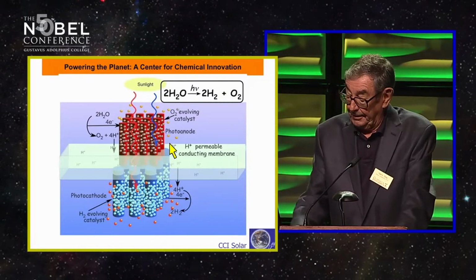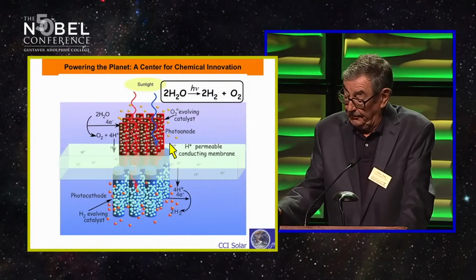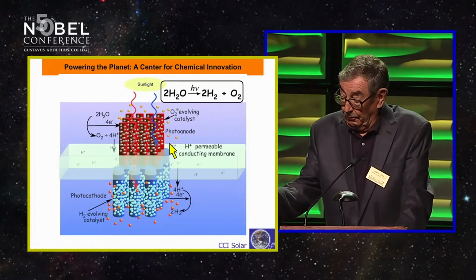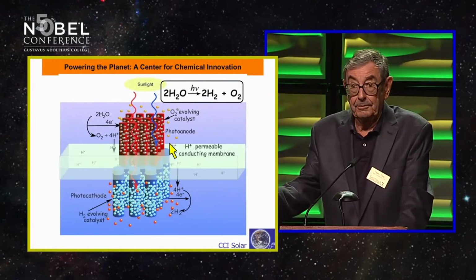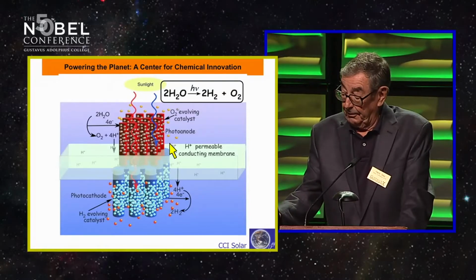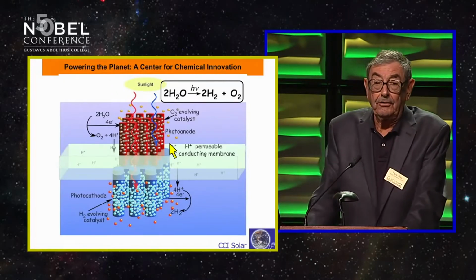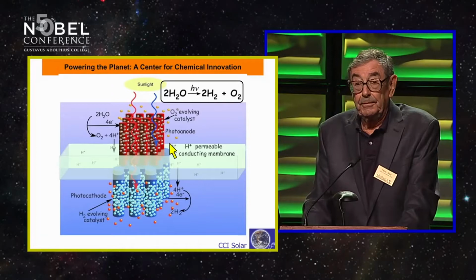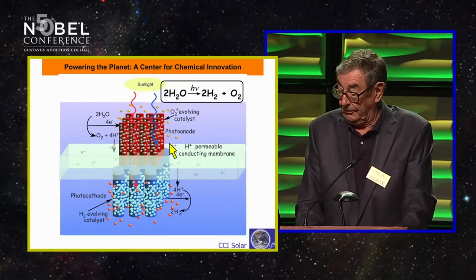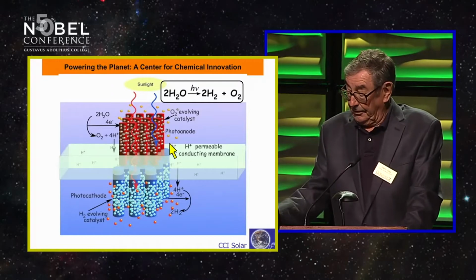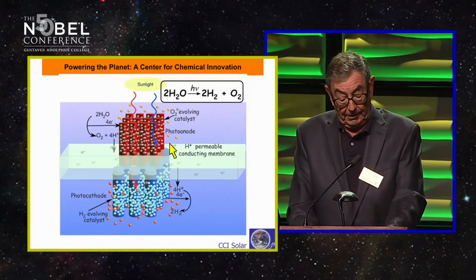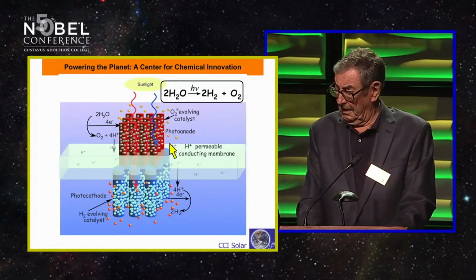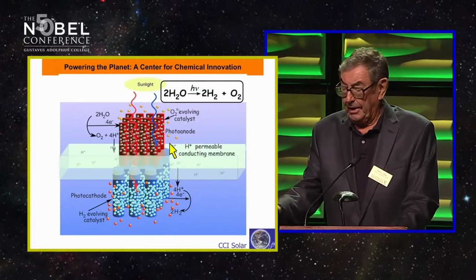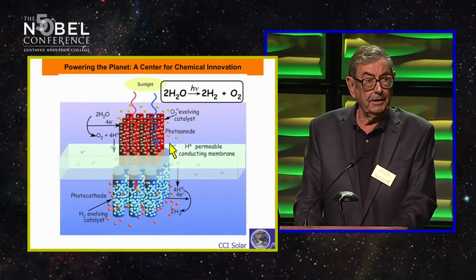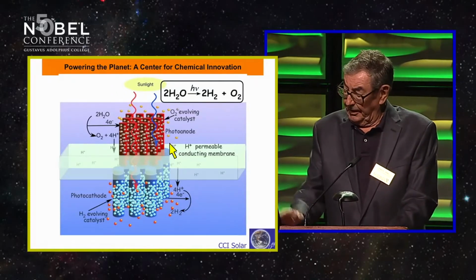Same is true in the photocathode, which is a silicon microrod. We make these silicon microrods, and the red light that comes through after absorbing the blue and green up here excites the silicon band gap. We want to get the electrons to the surface with high efficiency so they can meet a proton with a catalyst to make hydrogen. So oxygen up here, hydrogen down here, with a membrane separator. That's the device model. Now, I'll tell you where we are along the way, because we've gone a long way in building these devices now, these integrated components.